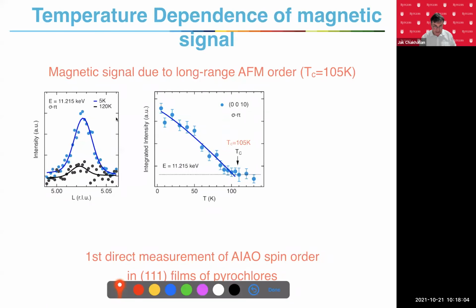So this is the integrated intensity of scattered light, which is proportional to the magnetization. That's the temperature. And you see a very beautiful long-range order, like you expect in the antiferromagnet, and that's a particular Q vector. So this is the very first report, what we're reporting today, of this exotic all-in, all-out, this 4-in, 4-out magnetic order in these Weyl semimetals.